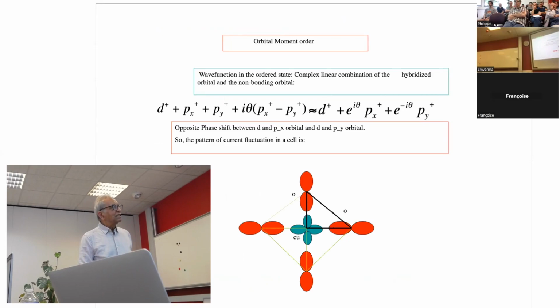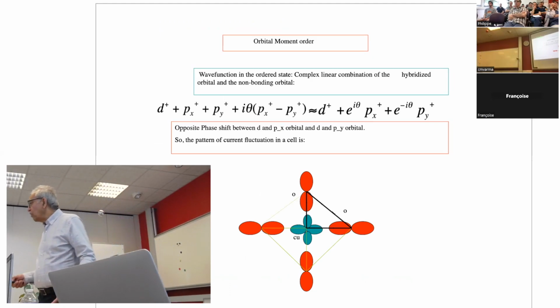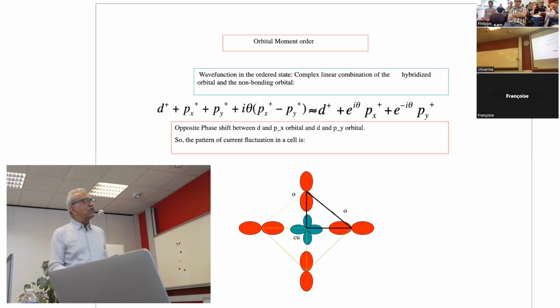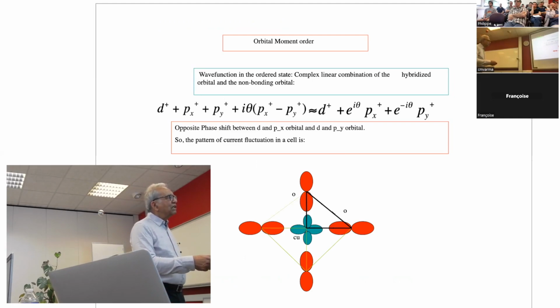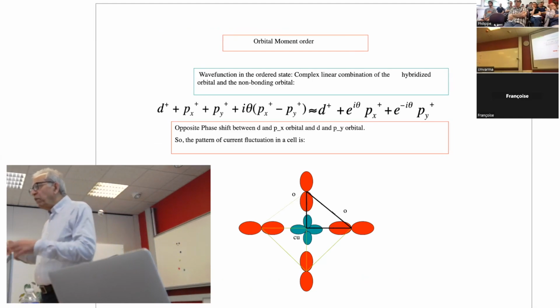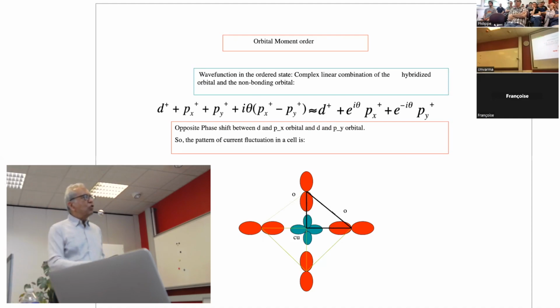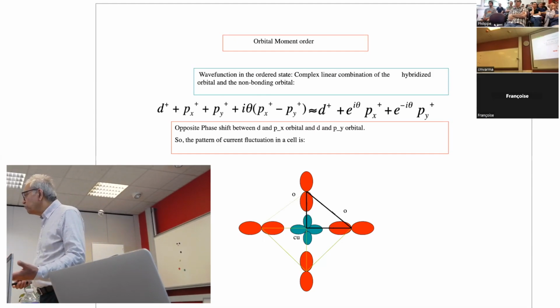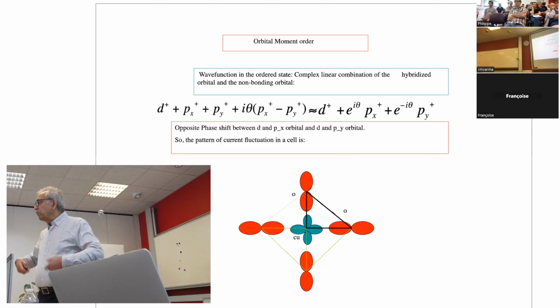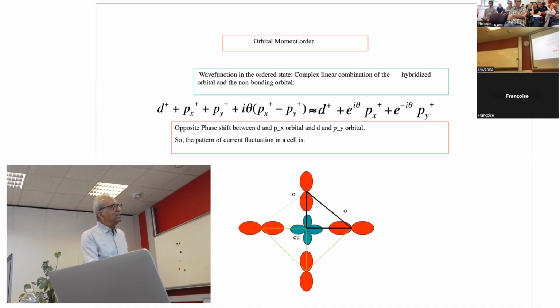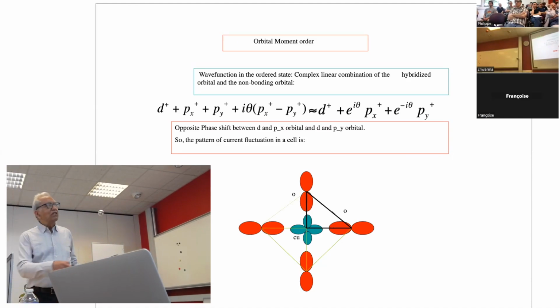Now, what we are really saying is that are there interactions which mix the orbitals of copper and oxygen non-interacting? So what are the orbitals of copper and oxygen? Well, there is an orbital which is a linear combination d plus px plus py, or d minus px plus py, the bonding and the anti-bonding orbitals of copper and oxygen. And there is one orbital which is px minus py, that's the non-bonding orbital of oxygen, which doesn't hybridize with anything in the simple tight binding orbital. Imagine you have interactions such that these can be mixed, and they are mixed with an imaginary component, or a complex component, but something with an imaginary component.